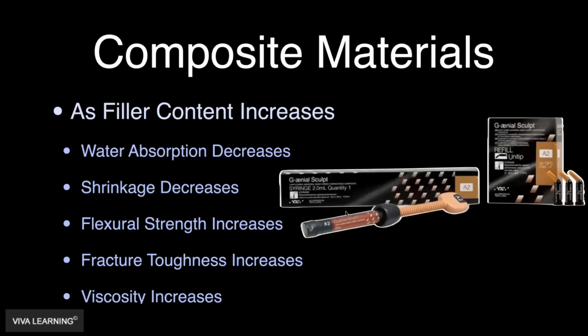And if you've been practicing, you'll know that we did that by working on the filler and changing the filler. So we went from macro-sized particles to micro-sized particles, and from micro-sized particles to nano-sized particles, because one of the things we learned is the smaller you make the filler particles, then the more of it you can put into the resin matrix, the monomer, without having a viscosity problem. The material becomes too viscous.